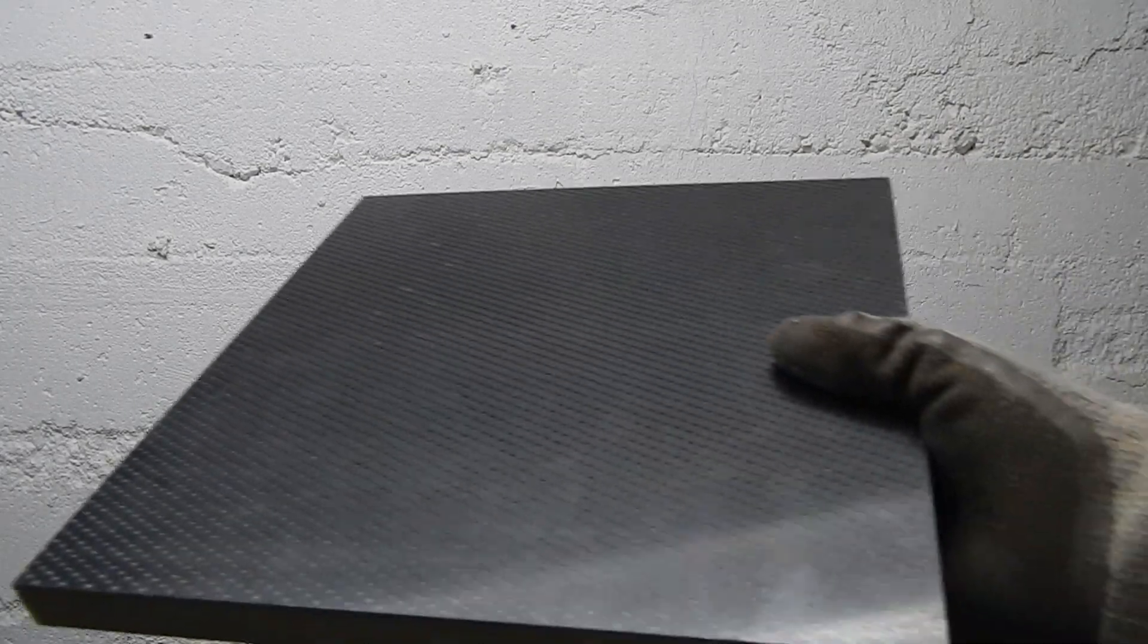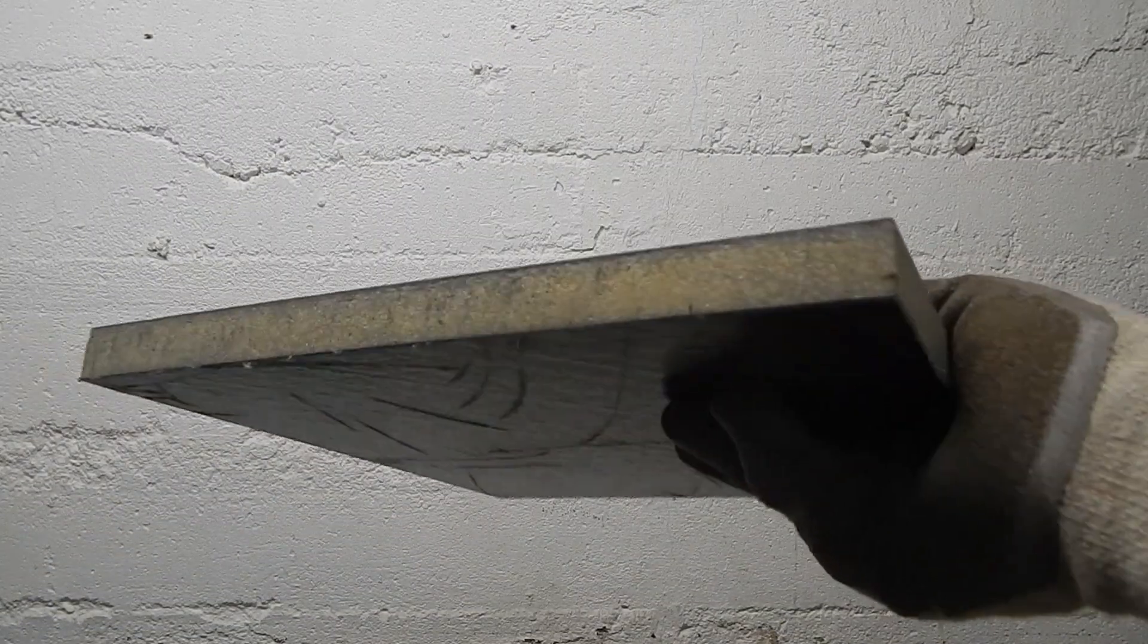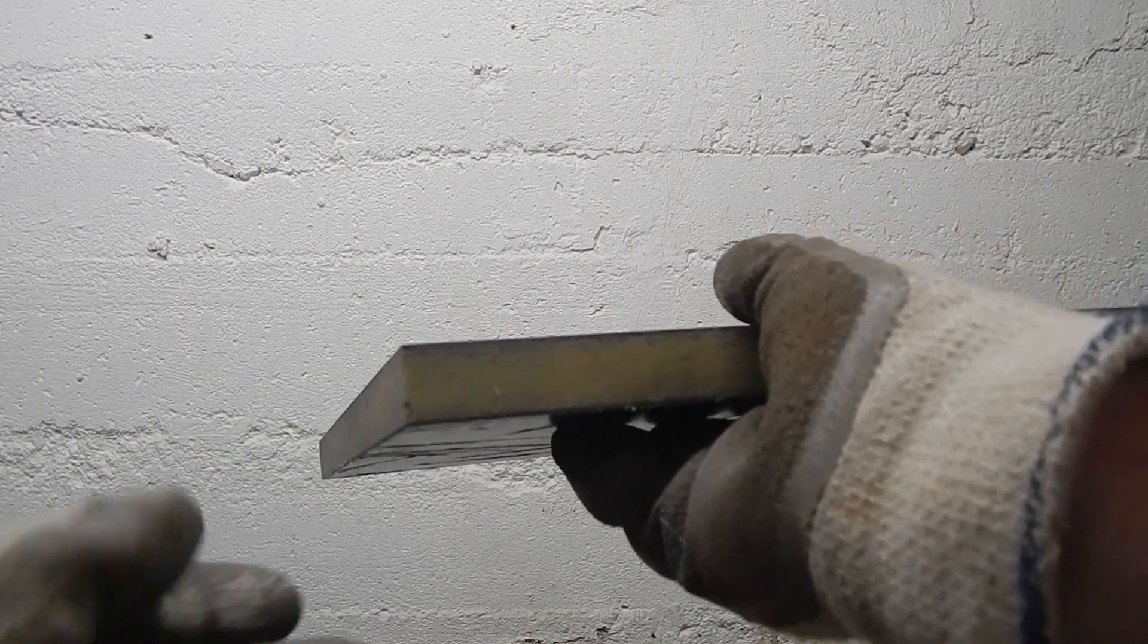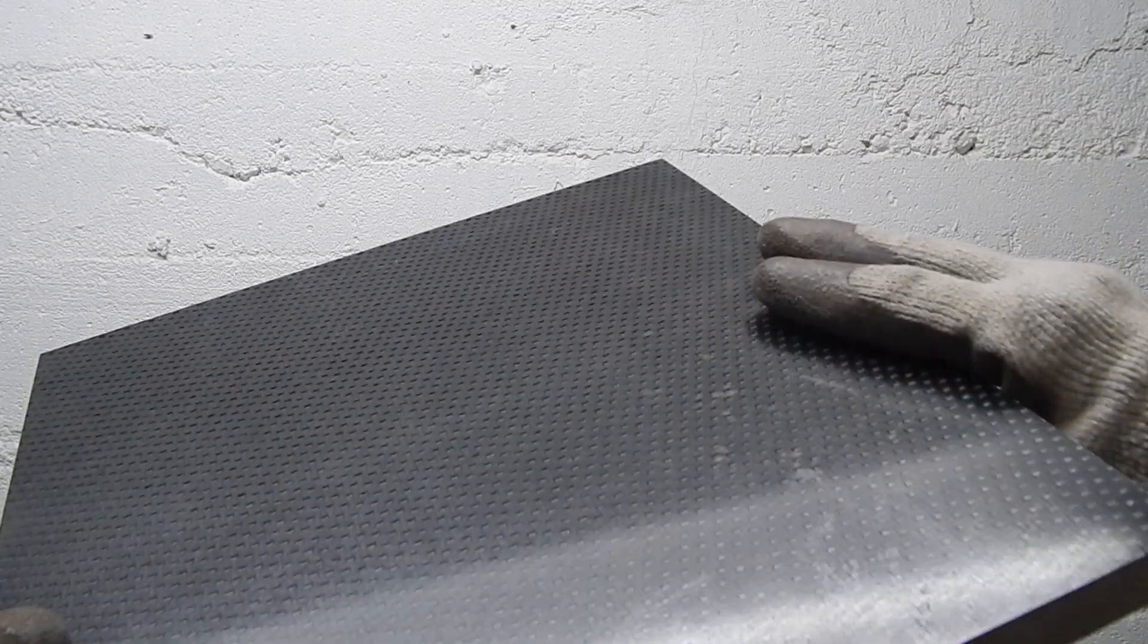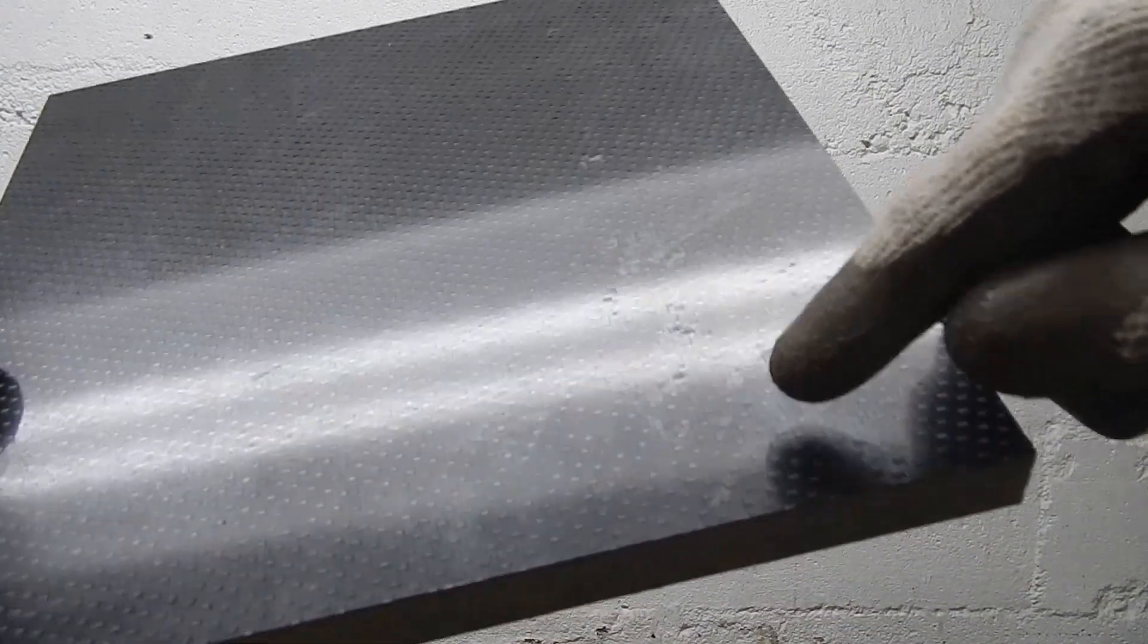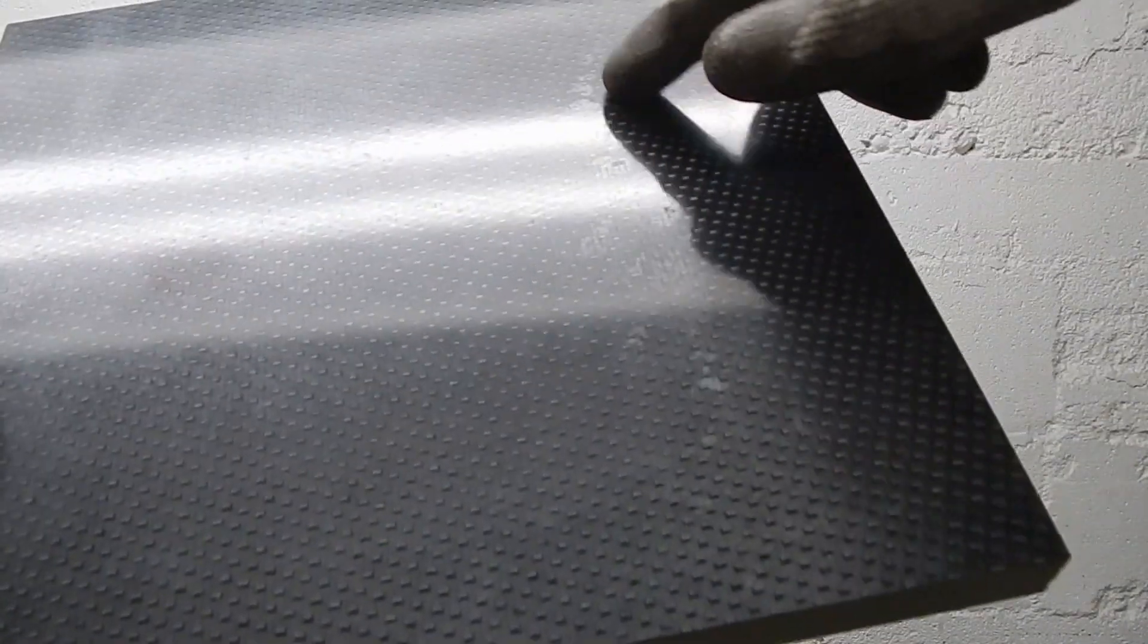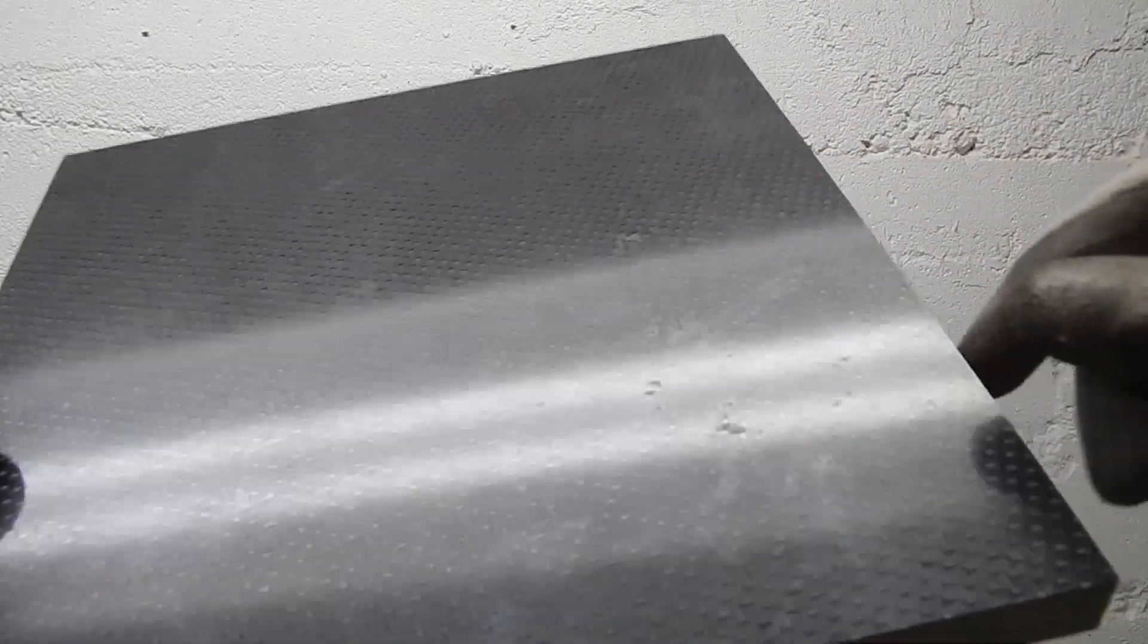Having a look at the finished panel, trimmed, you can see it's pretty nice. You can see the spray adhesive there, the little run of it that caused that bottom skin to look a little gross. There was more air in here than would be ideal. I think that having the fill get choked off at the very end. Yeah, there's the spray adhesive, you can see that line of splatter. That was not the best.